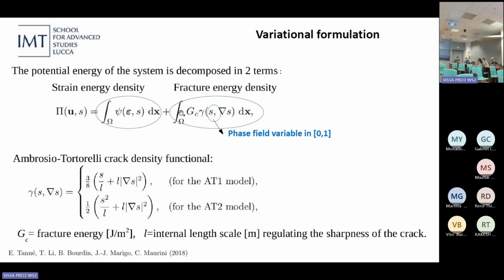And here we have a second integral, which is basically the fracture energy density, in which we can see a constant here, which is the fracture energy of the material, and this gamma function here, which is the so-called crack density functional or Ambrosio-Tortorelli functional, which is a function of the phase field variable, so the damage variable, and its gradient. This approach is called regularized because via gamma convergence, if we let this L, which is basically the main character of the story, the internal length scale of the fracture, go to 0, it is proven that this functional converges to a discontinuity in which the integral over omega is replaced by an integral on the effective discontinuity, so the crack inside the material.